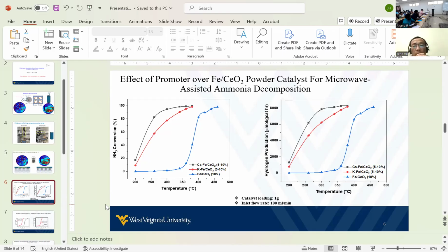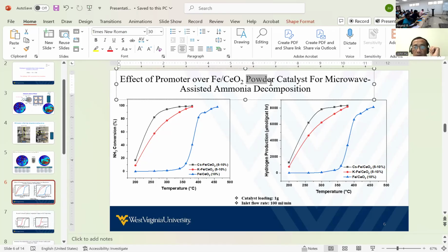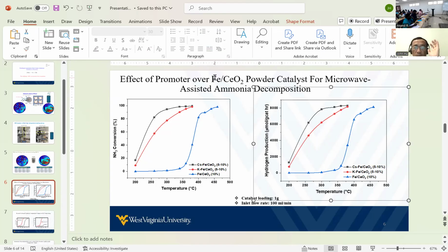Now when we try to select the catalyst, the so-called active ingredient, to be coated on the monolithic, we have to do powder testing. Powder testing means the ingredient. In the next couple of slides we want to coat the powder on the monolithic, and here we want to compare iron on ceria. In terms of ammonia decomposition, it's very similar to ammonia synthesis because you need promoters. On the left-hand side is ammonia conversion, and we start with iron on ceria, then potassium-promoted iron on ceria, and cesium and iron.